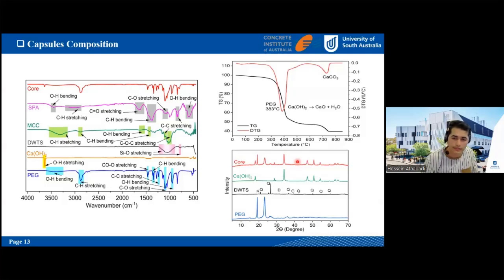Some forensic tests have been done to identify the structure of the capsules. All these tests actually confirm that the core material, because we use PEG, polyethylene glycol, as a kind of binder to bind all the powders we have together. So all these results show that the PEG actually granulated all these core materials together. So if you see the peaks, all the peaks are in the final core material peaks.